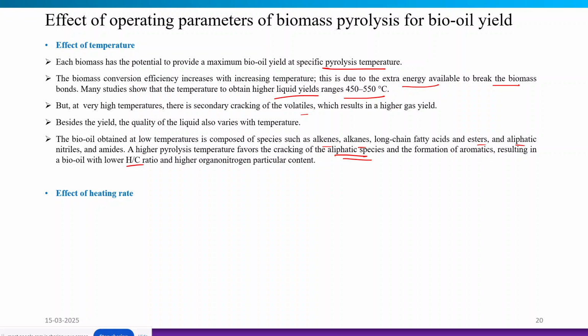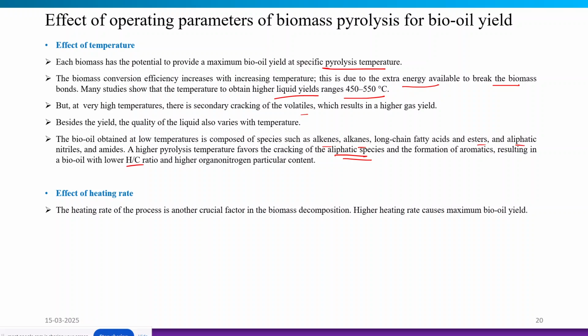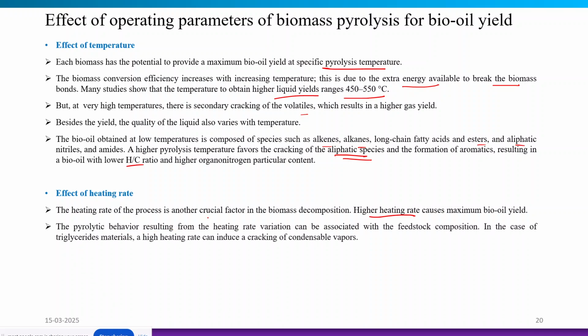Now, the effect of the heating rate. The heating rate of the pyrolysis process is another crucial factor for biomass decomposition. We already discussed that fast pyrolysis, with a higher heating rate, causes maximum bio oil yield. The pyrolytic behavior resulting from heating rate variation can also be associated with the feedstock composition. In the case of triglyceride material, a higher heating rate can induce cracking of the condensable vapors. Faster heating probably inhibits the secondary dehydration reaction, resulting in a reduction of the water content in the bio oil. That's why fast pyrolysis is mostly preferable for the production of bio oil.